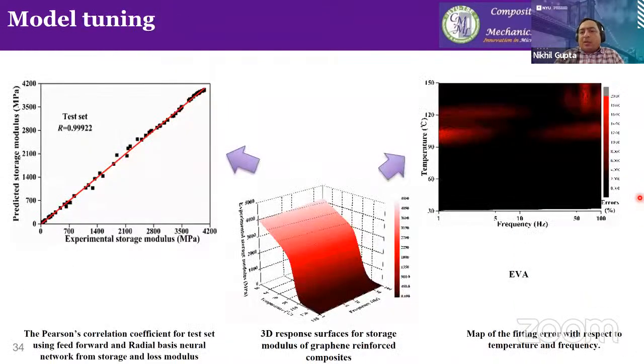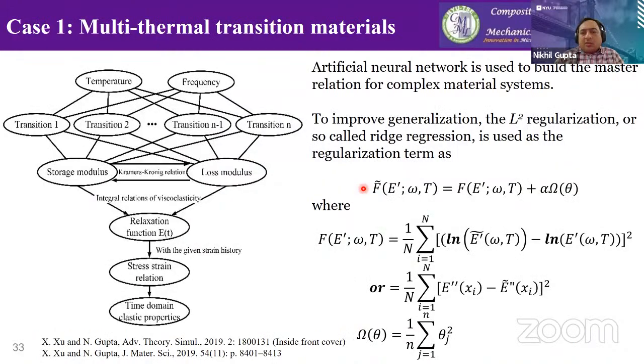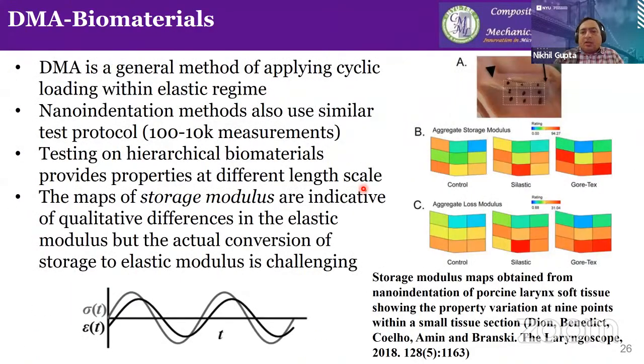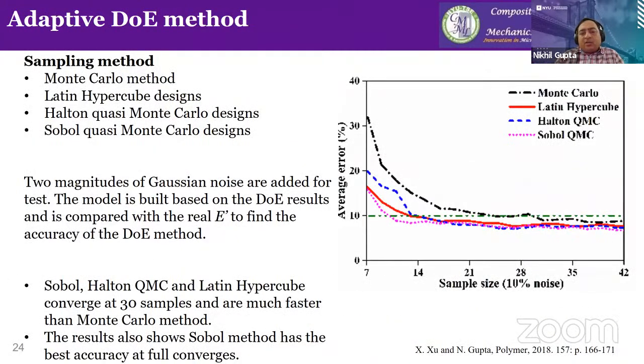So here you see this heat map. Oh, sorry, let me go back. You asked about the interpolation methods actually. The comparison is right here, and it depends upon the type of data that you have and the nature of the data. If you were applying just a standard Monte Carlo method, you need about 25 data points before you can get to the average error of about 10%. This average error is a little bit of a misnomer simply because there are a couple of points which are very high in error, and most of the graph has much lower error. So with 25 points, if you were taking the same 14 points here as with the other methods for Monte Carlo, your error is going to be much higher in that case.